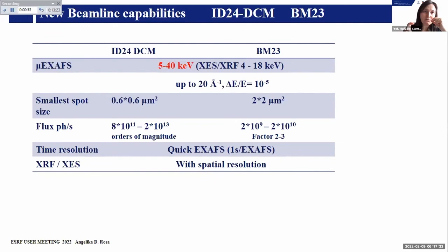And do you have an estimate of what will be the enrichment that you need to have a sensitive enough analysis, or what is the order of magnitude in general that you need to go to? So we did some experiments on rhenium L3 edge, for example. For now, at BM23 or at BM beamlines, we could actually see XAFS or XANES signal down to 100 ppm. We did not test yet, of course, how far we can go in dilutions for these elements at ID24, but we are planning just now a test experiment at BM23 on these edges.